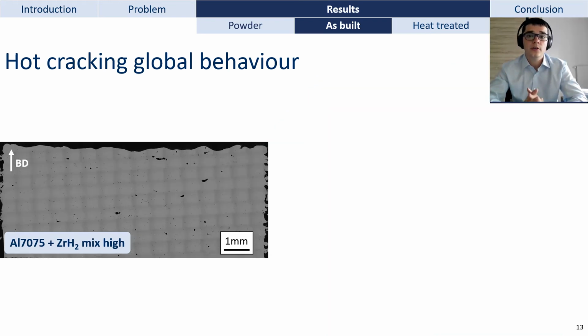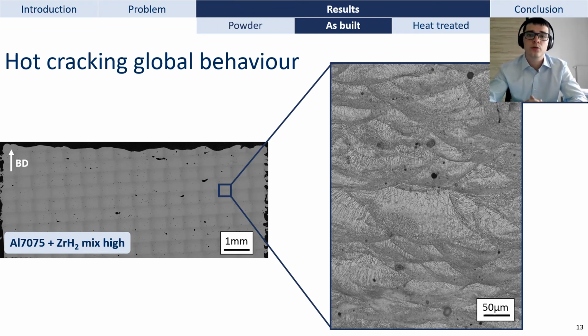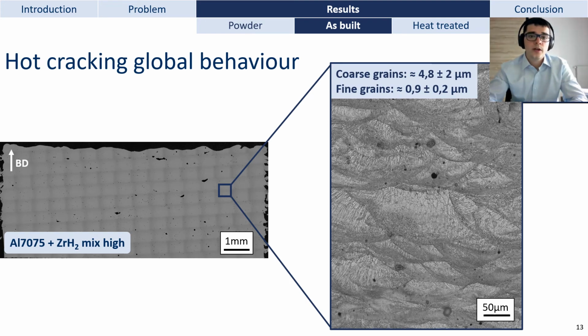Now, if we look at the high content zirconium alloy, we can see that the hot cracks successfully disappeared. It can be explained by its microstructure, where no more grains cross the melt pool boundaries. Moreover, the fine grain regions occupy a larger portion of the microstructure, sometimes occupying entire melt pools. Even the coarse regions have grains smaller than for the low zirconium content alloy. However, the fine ones are about the same size, so it can be concluded that the zirconium content will influence the relative portion of microstructure occupied by small equiaxed grains. If not enough zirconium is added to the aluminum 7075, hot cracking cannot be entirely avoided for this processing parameter.